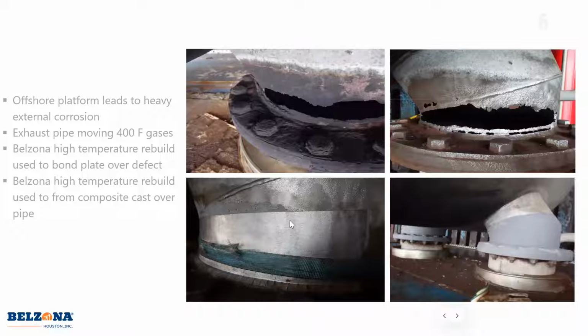Bonded this plate, you have that 5,000 PSI adhesion that's going to hold it down. On top of that, we used our material to wrap around and really create a cast. And that holds all the pressure in there, rebuilds that huge hole that you see there, and makes it stronger than it was before, corrosion resistant at the same time. So this might be a unique application that some people might not have even considered repairing.